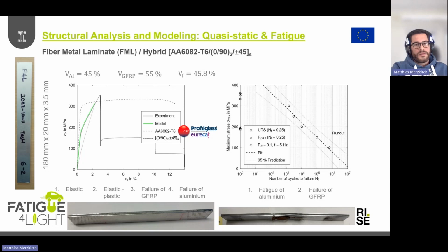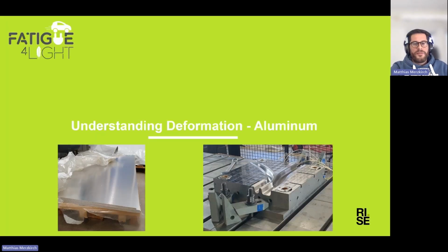So also crack growth here, at some point also delamination in between the layers, and then the final failure of the glass fiber reinforced part. So this is what we are working on in order to also understand a little bit about the deformation and failure behavior here. Now getting a little bit more complicated because we want to actually form the material here in